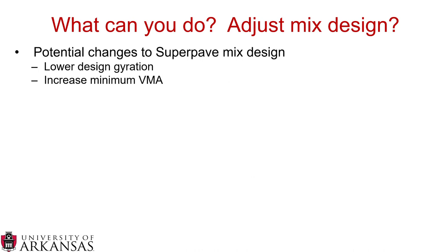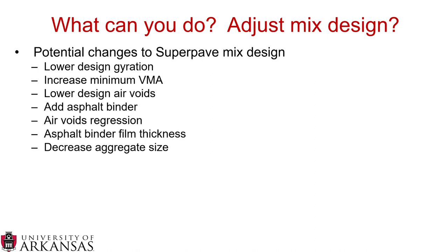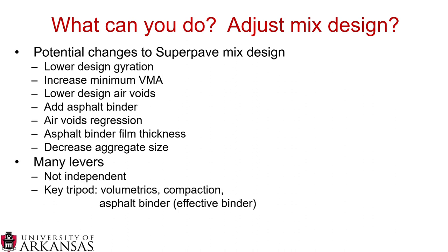Well, there are potential changes we can make to the Superpave mix design. We can lower the design gyrations to that Ndesign level. We can increase the minimum VMA. We can lower the design air voids or add asphalt binder. We can perform an air voids regression. We can increase the asphalt binder film thickness, or we can decrease aggregate size. Now, these are many levers and they are not independent. You can't just increase VMA and expect everything else to stay the same.